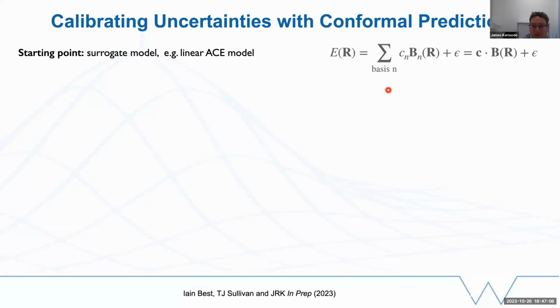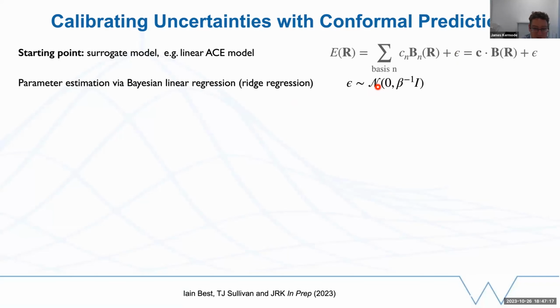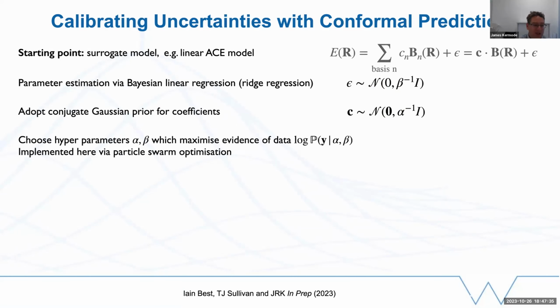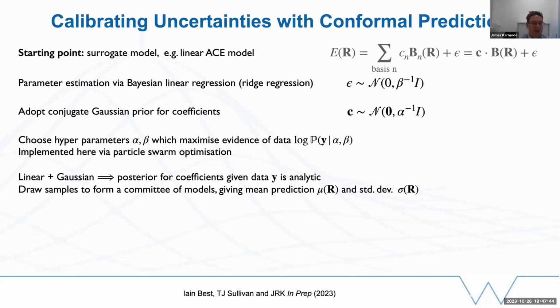We're using the ACE framework that I briefly mentioned earlier on. So we have a linear model, coefficients times basis functions. We assume some error, and we assume that that error is Gaussian, so it's random noise, essentially, with some standard deviation or precision. We assume that we know our coefficients should be small and also have some unknown Gaussian noise on them. And then we find the values of these two precision parameters using a Bayesian scheme, essentially, so we maximize the evidence. And that gives us a way of sampling different choices of models, all of which are compatible with the data that we've got.